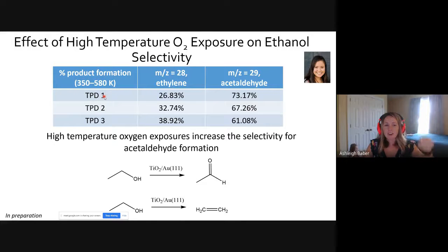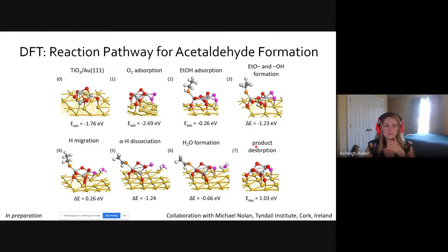And after that first TPD, where we're using up some of the oxygen within that titania and around that titania, we see that the selectivity decreases, and then that trend continues for the third TPD as well. So we see that oxygen definitely makes a difference.